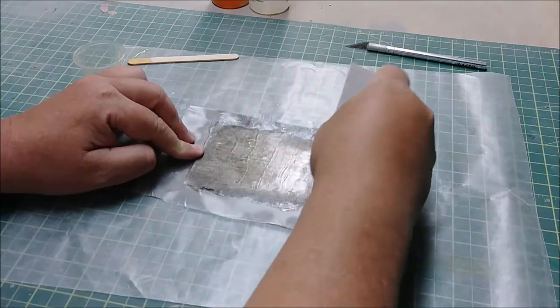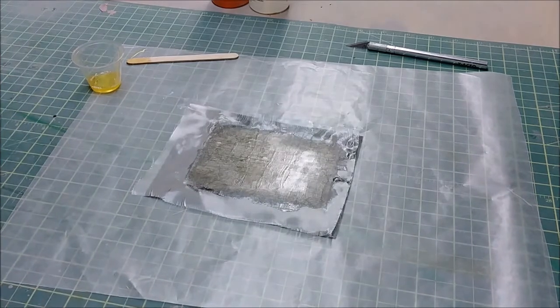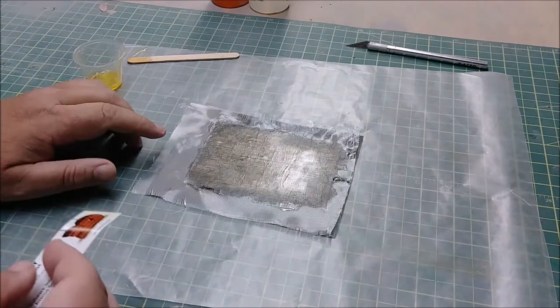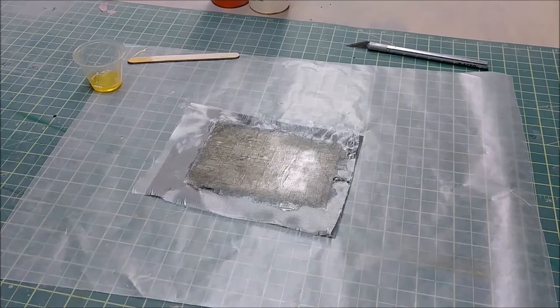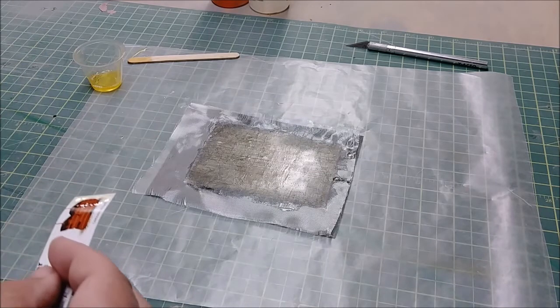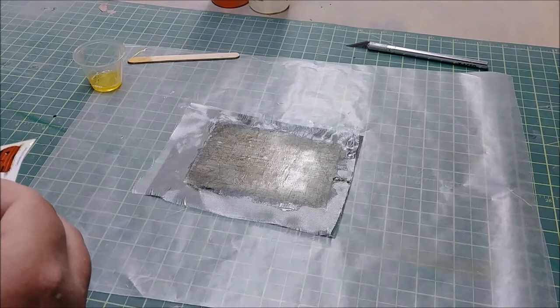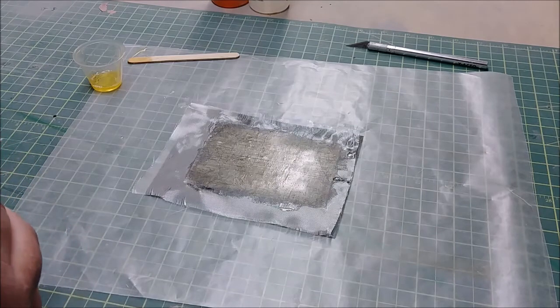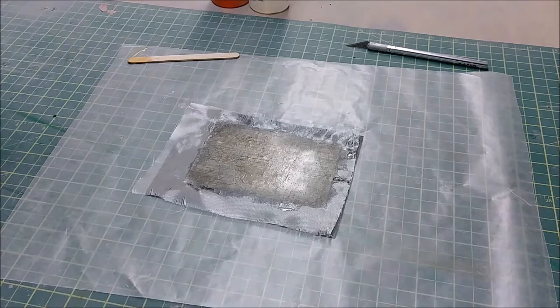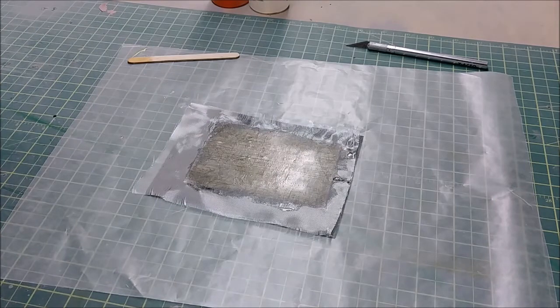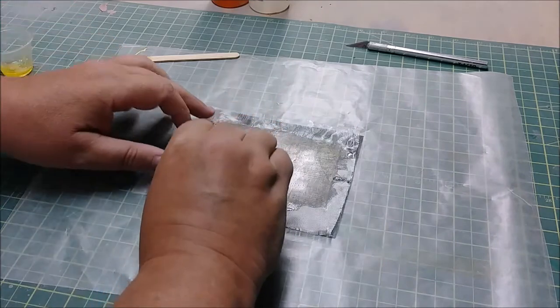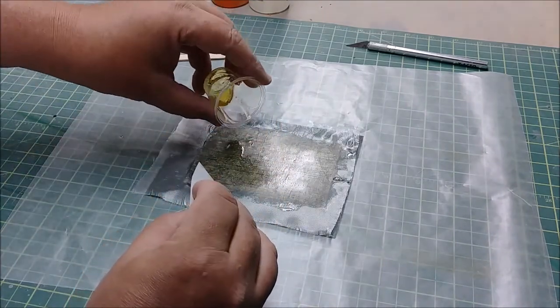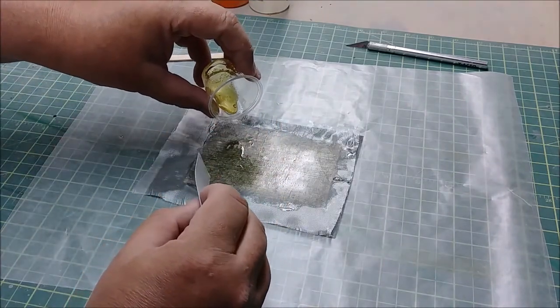So we're going to have a very lightweight hatch that is very, very strong. The offset I've made between my hatch and the area where the hatch sits is 3/32nds, and I'm using a 1/16th piece of balsa. So between the balsa, the two pieces of carbon fiber veil and the two pieces of glass, it works out, and by the time it's primed it all kind of levels up to about 3/32nds.